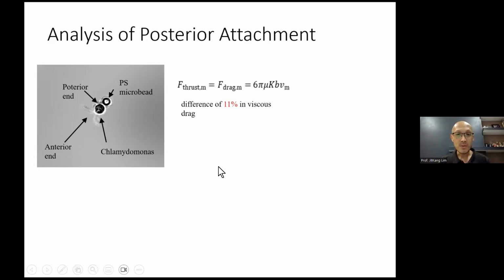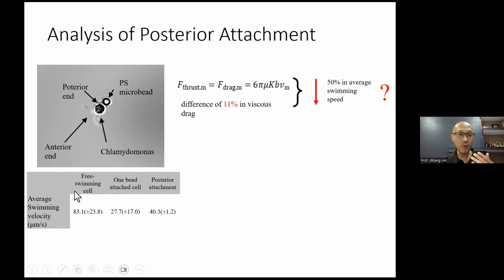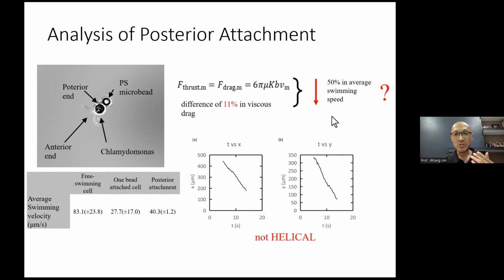And we managed to calculate the difference in terms of the viscous drag after attaching these microbeads. The difference is about 11% increment in terms of the viscous drag. However, if we look at the average swimming speed of this construct with posterior attachment, the swimming speed is roughly reduced to half. So in other words, it can't be answered by just having 11% of physical drag difference. It can't explain the 50% swimming speed reduction.